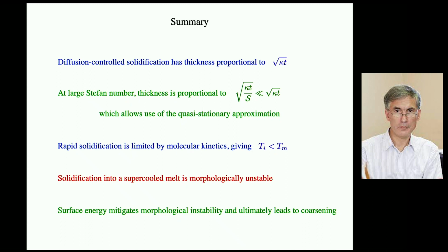I've done all of that, and you can do it. It's just much messier on these slides. But yes, then the kinetic undercooling is G, the kinetic growth rate, times the difference between your equilibrium minus the actual temperature. The equilibrium would then be depressed by your curvature term, by the Gibbs-Thomson.